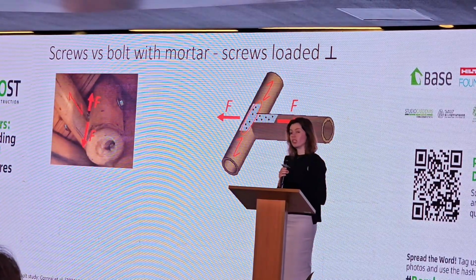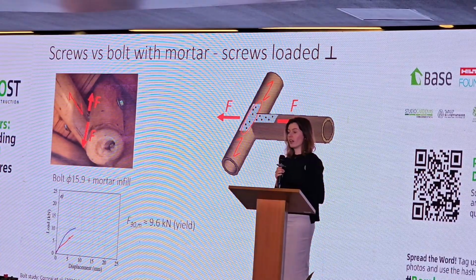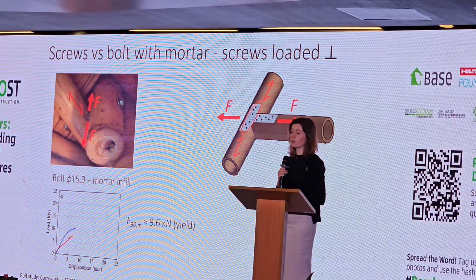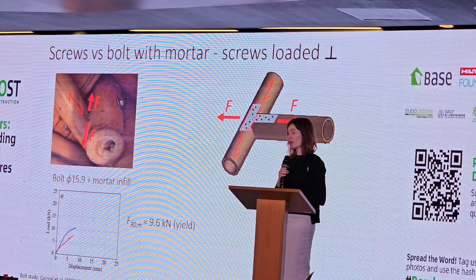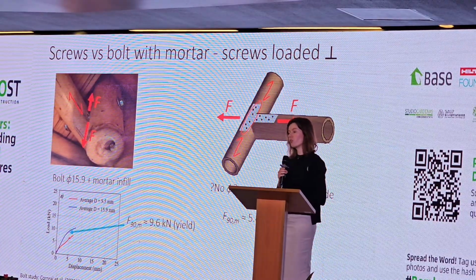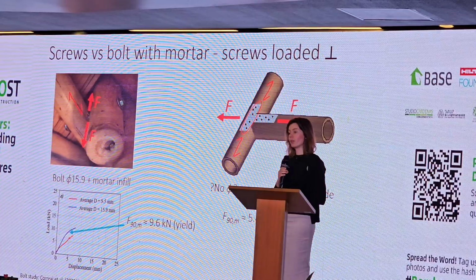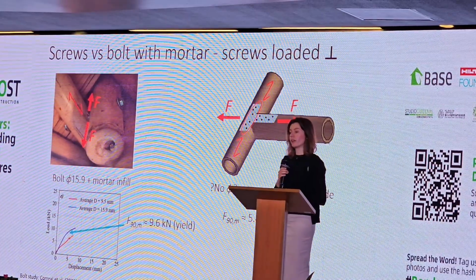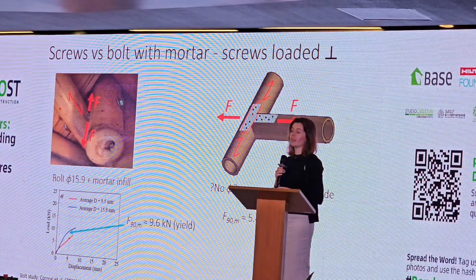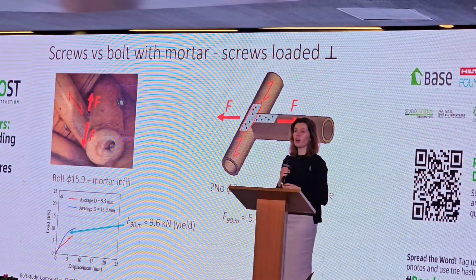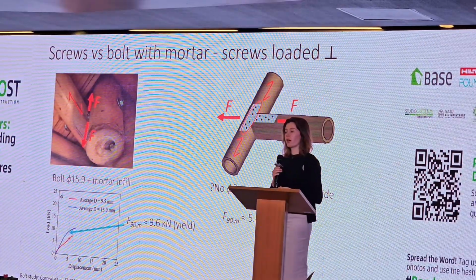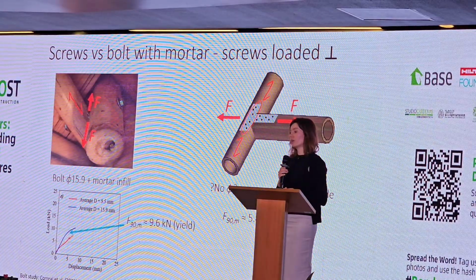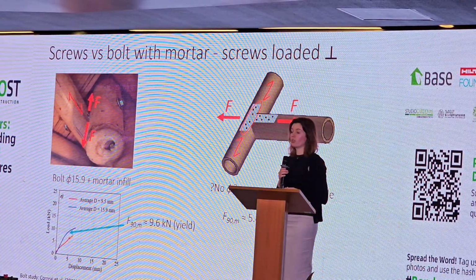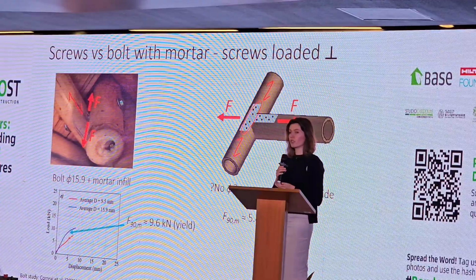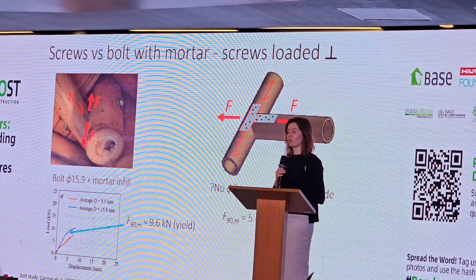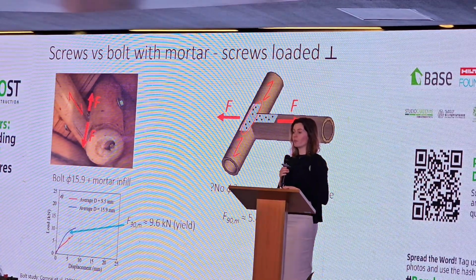What about the perpendicular load? So this is the tricky one. The study I mentioned found the capacity is about 10 kilonewtons. With screws, we can only get around 5, and the reason is that as long as the screws are near the center line of the bamboo, you cannot really multiply the number of screws. It's just one crack line, and it's just 5 kilonewtons that we can get. There are a lot of assumptions here. Maybe it's 4, maybe it's 6, but it will be quite difficult to get it to 10 without more research.